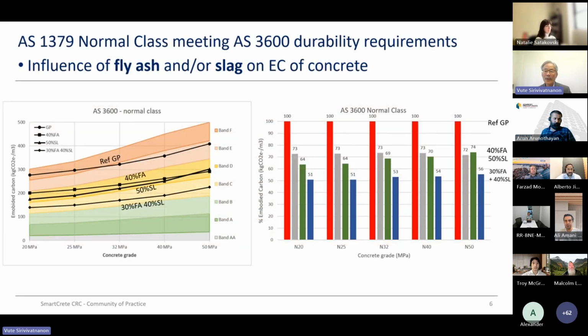So we use the same methodology to calculate our embodied carbon. And this is just to highlight what you can save in terms of the embodied carbon. The graph on the right shows the embodied carbon of different binder systems in comparison to a general purpose cement system. With fly ash and slag binary system, you can save up to 30% embodied carbon compared to a general purpose cement system for all the different grades of concrete. If fly ash and slag are available and the plant is capable of handling three materials, you can then produce concrete with triple blend and a potential saving of embodied carbon of up to 50%.